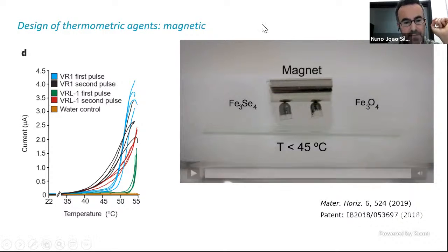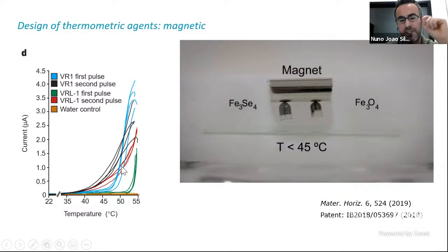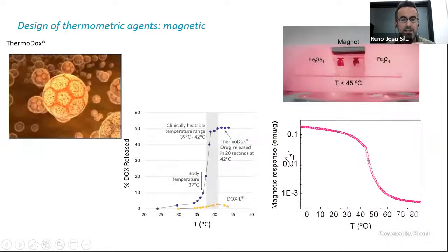So again, it's something reminiscent of what happens in nature, something that has a click. It gets on and it gets off at this temperature here. So basically, the magnetic response is this one here. It has a high magnetic response below this 45 degrees Celsius, and it has a low magnetic response above this temperature. And you can see this is a logarithmic scale. So this is a huge change of magnetization in a very narrow temperature range.